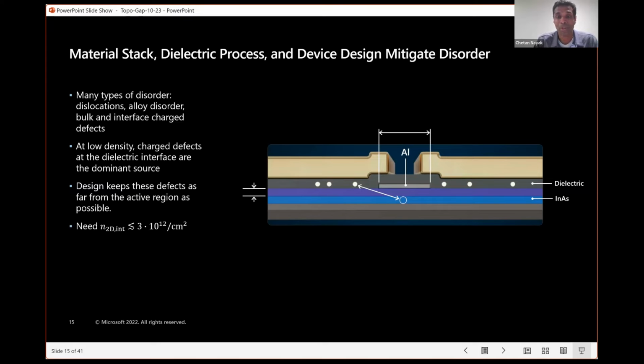Once we have optimized those, made the aluminum as wide as possible but still depletable, and made the barrier layer thick enough but still inducing a healthy induced gap, then in that circumstance we need a density of charge defects that's less than around 3 times 10 to the 12th, from our simulations. And so that's the target. And we've developed fabrication processes that indeed minimize the density of such defects.